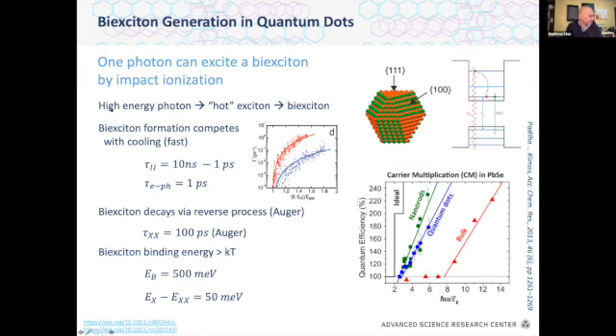So again, this is probably familiar to most people. You take a high energy photon, which creates a hot exciton in a semiconductor. Your hot exciton has two possibilities to cool. One way it can cool is using just conventional multi-phonon emission, relaxing to the band edge in the way you were used to with most hot exciton systems, or alternatively it can undergo a process called impact ionization, where instead of cooling by emitting phonons, it cools by emitting a second electron hole pair, with all the caveats about energy conservation coming into play.